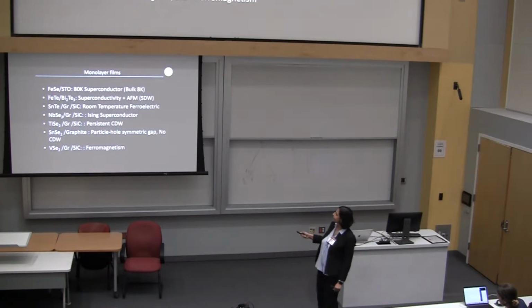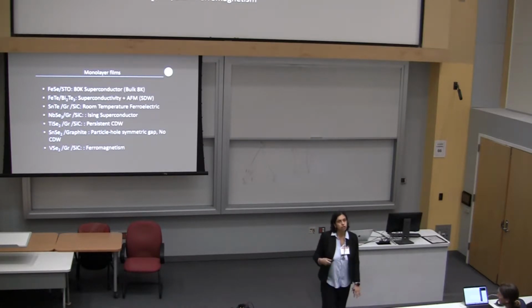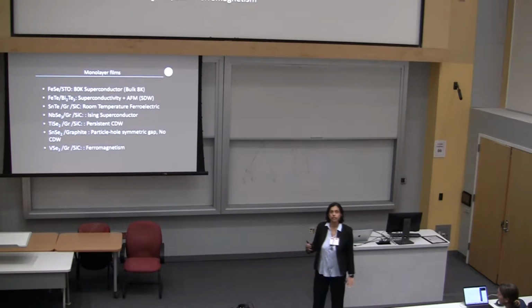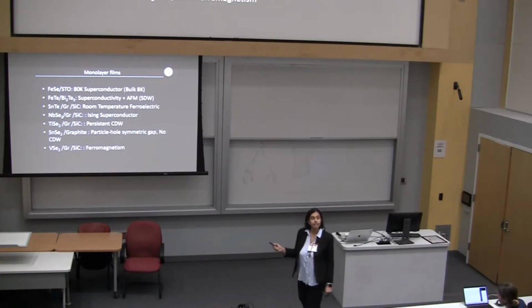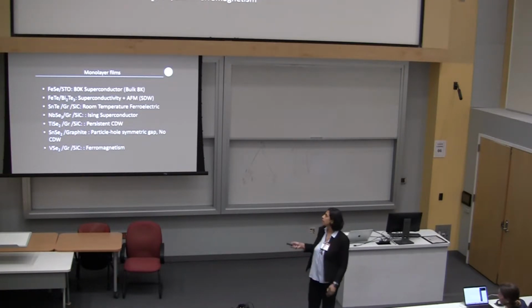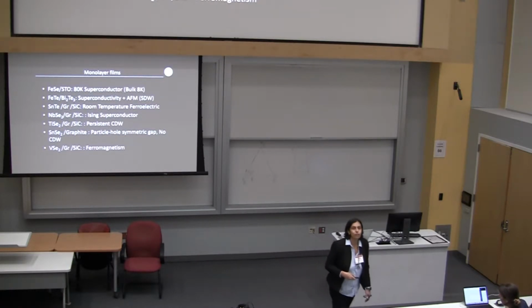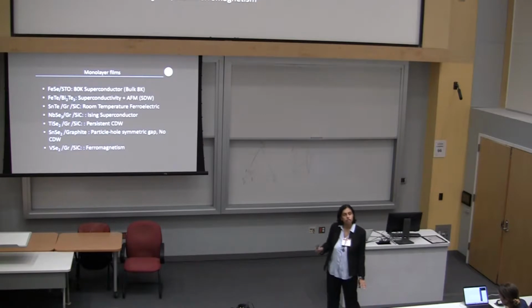This is, so FeSe, FeTe, tin telluride, these are not transition metal dichalcogenides. I just put them here just as examples to show you how materials can be very different in their thin film form. But let me just start with these. So I think a lot of you know this. Iron selenide is a very interesting superconductor. However, if you grow it as a monolayer, its Tc can go up by a factor of 10. Right? You can go from 8 Kelvin to 80 Kelvin simply by growing FeSe on STO.